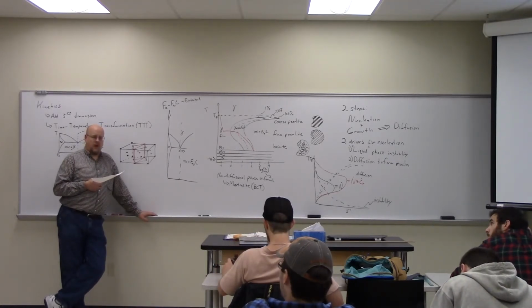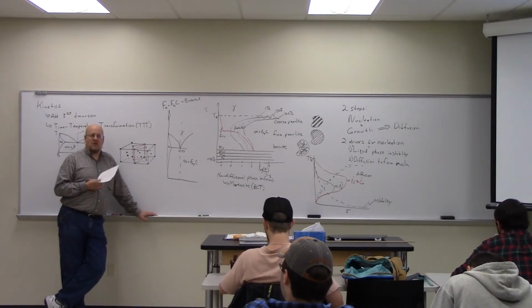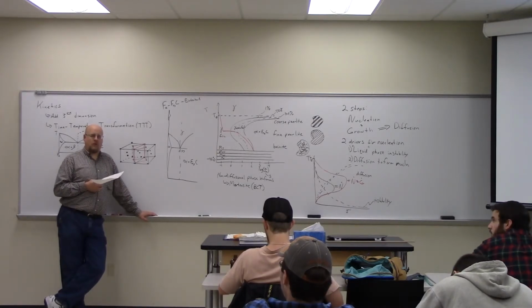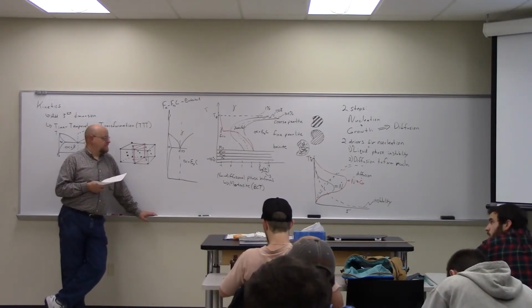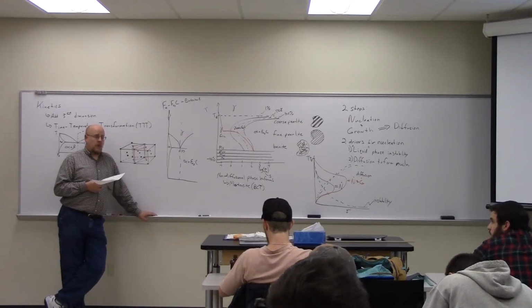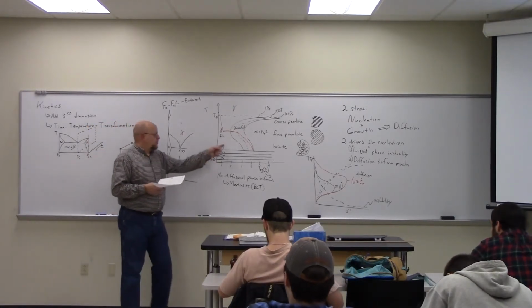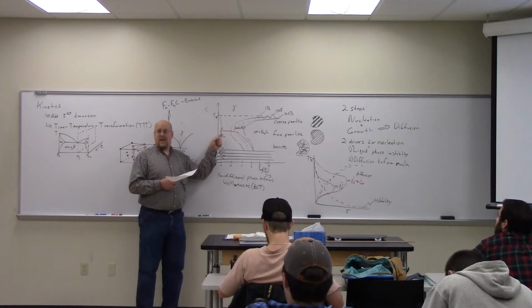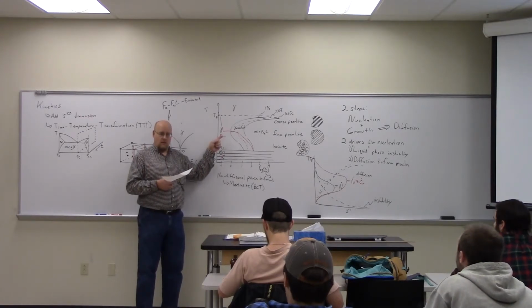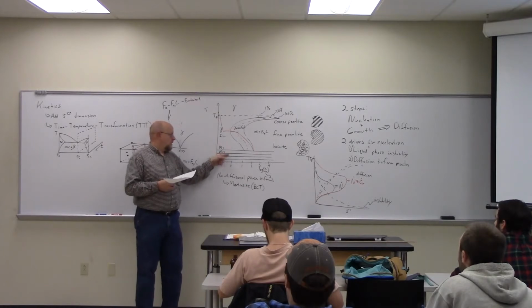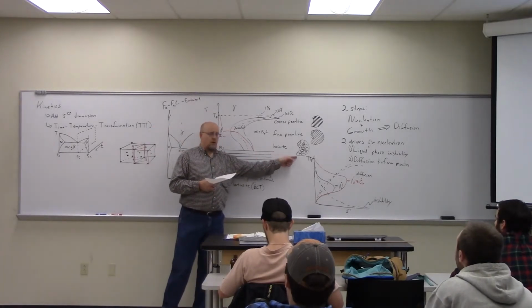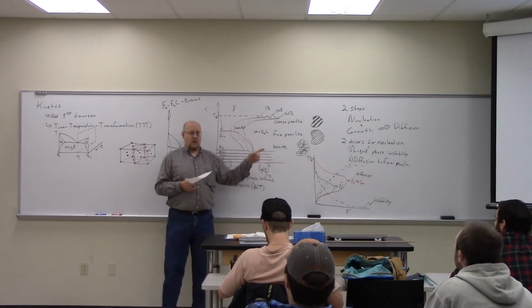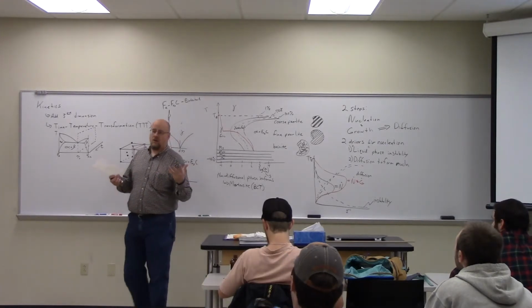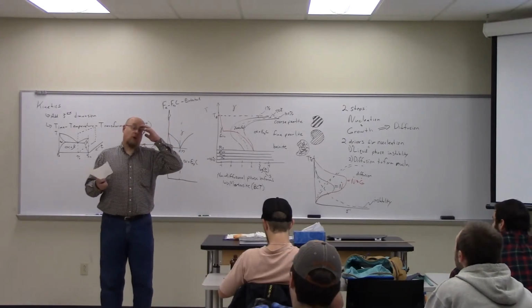Yes, at best. If you have martensite transformation, you're going to be working with something that's 90 to 95% martensite. However, what's really cool is once you get down into here, the gamma is locked in. If I get down to here and I let it go for a long time, the gamma doesn't change to bainite or anything. The gamma is locked in as gamma. It's room temperature austenite.